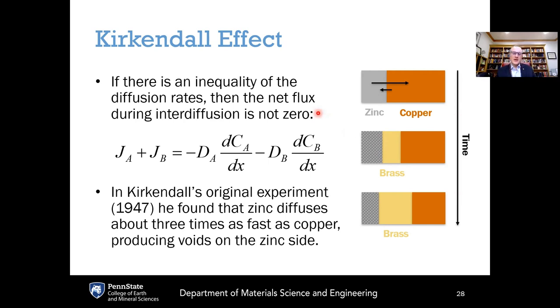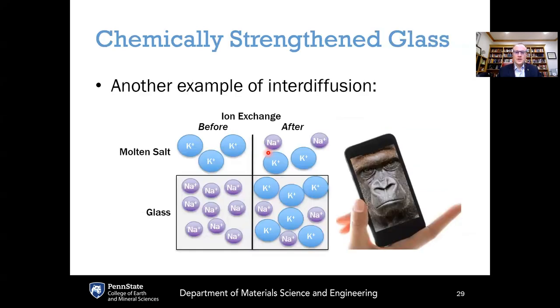So if there is an inequality of the diffusion rates, then the net flux during the interdiffusion process is not zero. So in other words, if you add up the fluxes of these two species, we need to consider separate diffusion coefficients for DA and DB because they are not the same, since the net flux is not equal to zero.